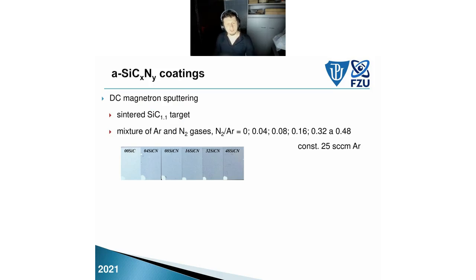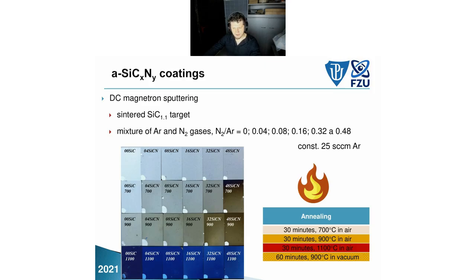So here are our coatings that were prepared using DC magnetron sputtering from a silicon carbide target. We used an argon atmosphere in our chamber and increased the ratio of nitrogen to argon in several different ratios, and these ratios give names to our coatings. So here you can see our several coatings, from pure silicon carbide to silicon carbonitride with increased nitrogen content, and I will show you very soon how this ratio affected the real composition of elements in the coating.